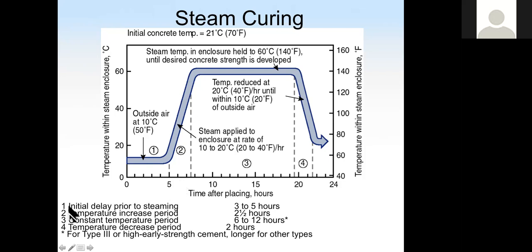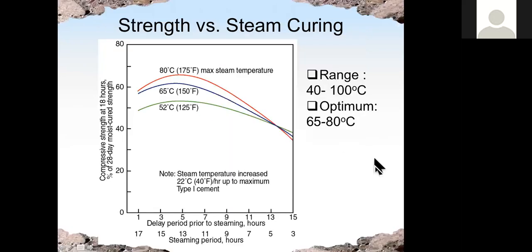But we also have the first stage, which is the initial delay. After we mix the cement with water, we need to let the concrete hydrate for several hours before we put it in the steam curing. Then inside the curing chamber it lasts around 6 to 12 hours, and then we slowly decrease the temperature before we take the concrete out. And here shows how the curing temperature and also the time period, which we call the delay period, before we do the steam curing, affect the strength of concrete.